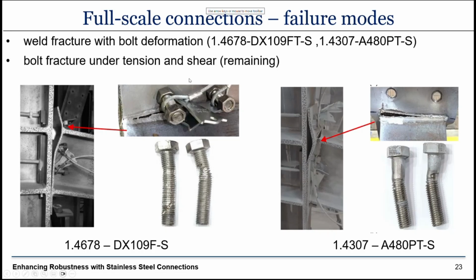So we obtained 2 distinct failure modes at ultimate: weld fracture with significant bolt deformation, and these are the 2 specimens that failed by weld fracture with significant bolt deformation. I believe it's very clear that here the bolts were almost at the end of their capacity. Here you can see clear signs of shearing of the bolt, so you have tension and shear in the bolt, and at the same time we got fracture of the weld.